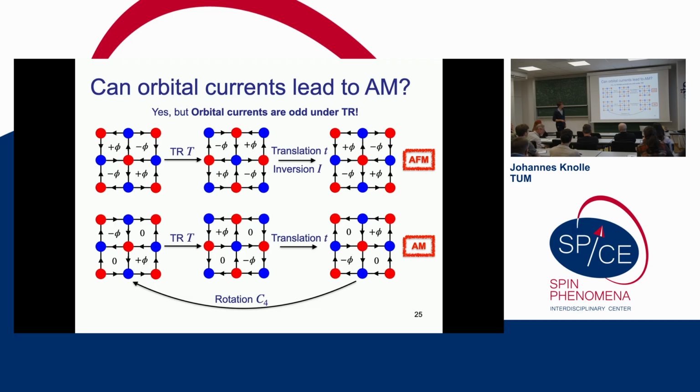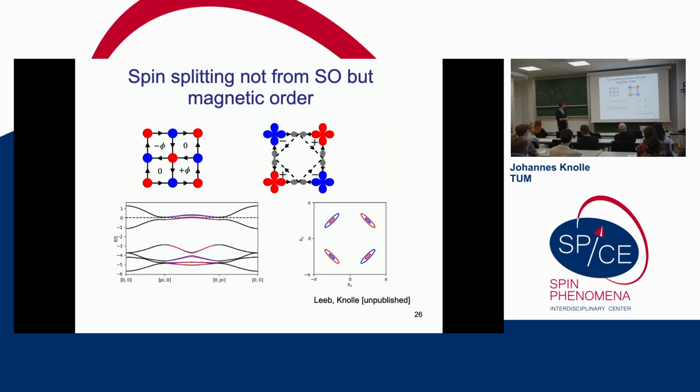Now the new message here is that if we take these states and put in just simple Néel ordering, then the coexistence of standard Néel ordering with these flux patterns, either here on the simple lattice or here on something like an Emery-type system, you still get the spin splitting out of that. Okay, so you can have the coexistence again of two orders. It's again interaction induced, even though we don't really know the interaction for the loop currents. But you would have the same thing: the coexistence of two orders giving us an altermagnetic state. Okay, good. So that's the main part.